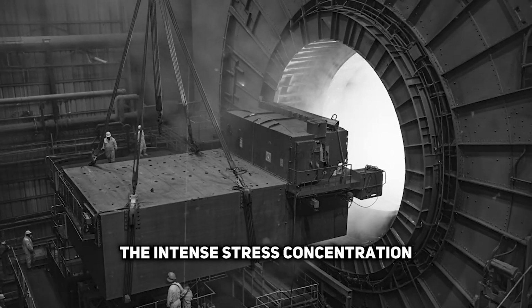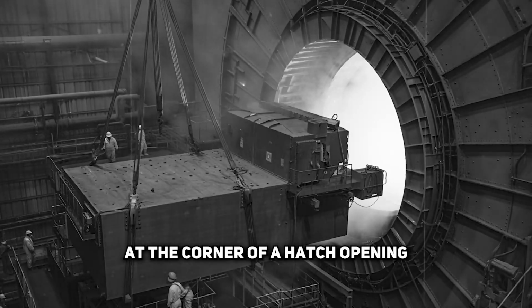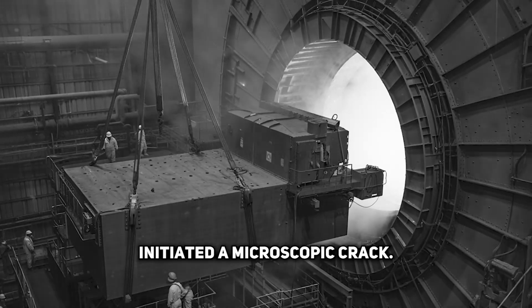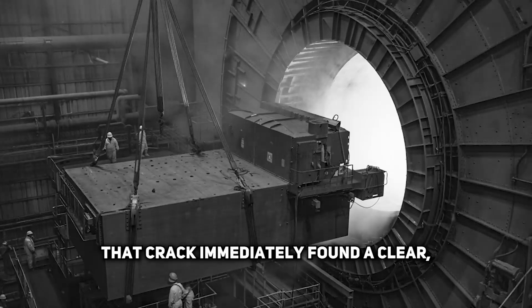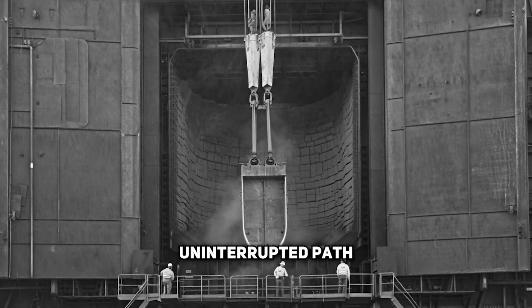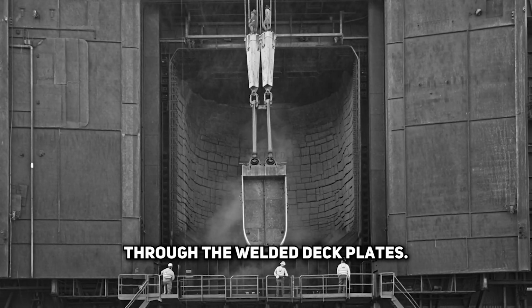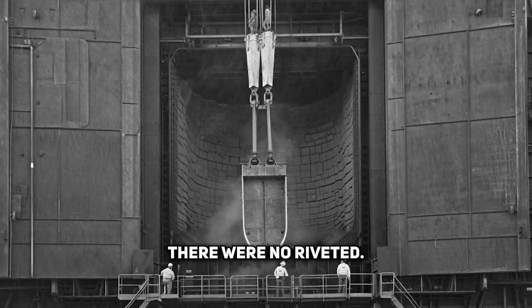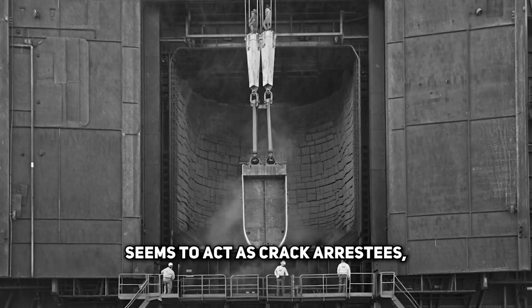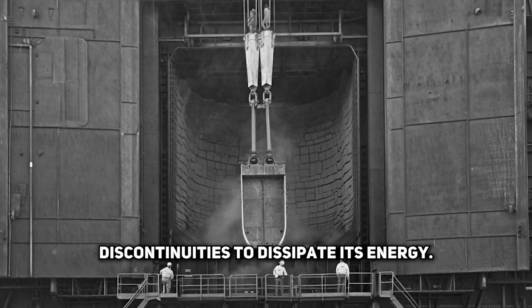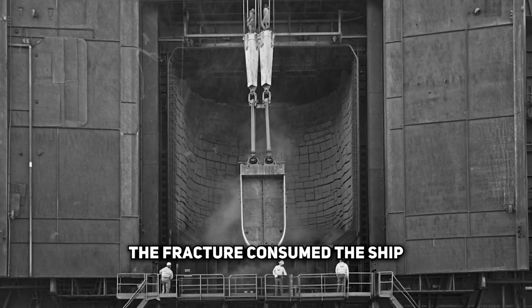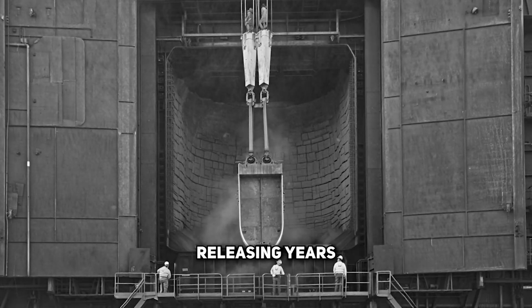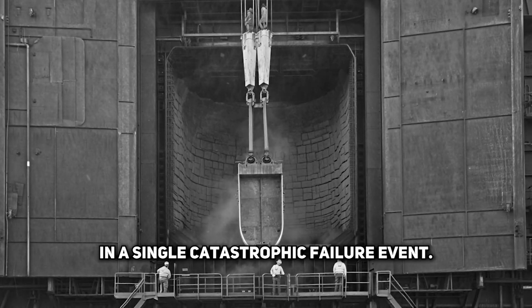The intense stress concentration at the corner of a hatch opening initiated a microscopic crack. That crack immediately found a clear, uninterrupted path through the welded deck plates. There were no riveted seams to act as crack arresters, no structural discontinuities to dissipate its energy. The fracture consumed the ship in seconds, releasing years' worth of stored energy in a single, catastrophic failure event.